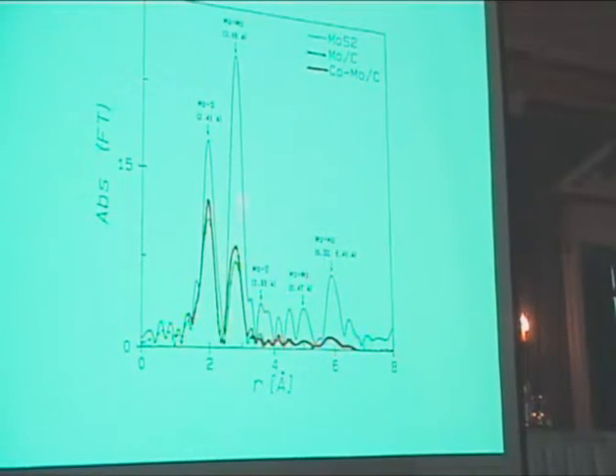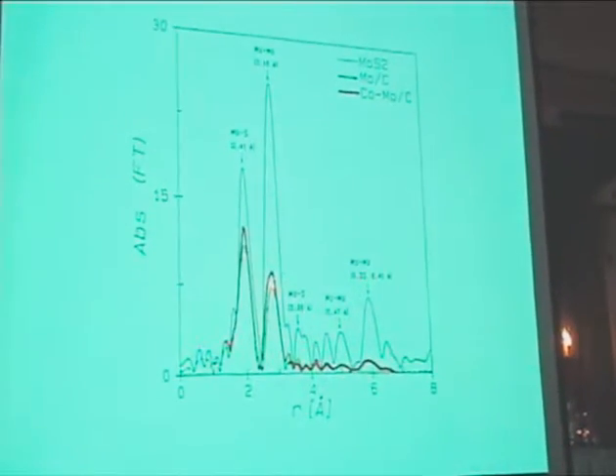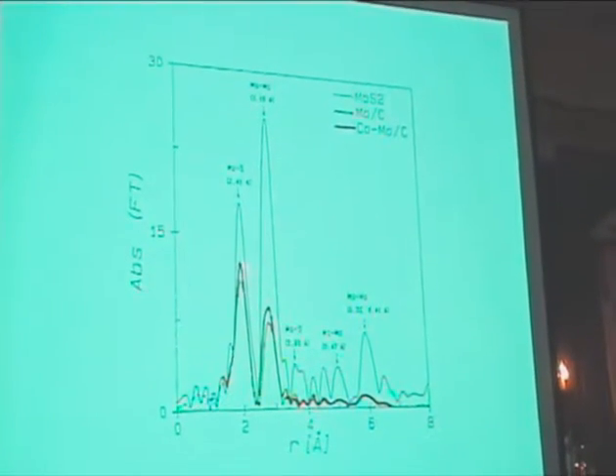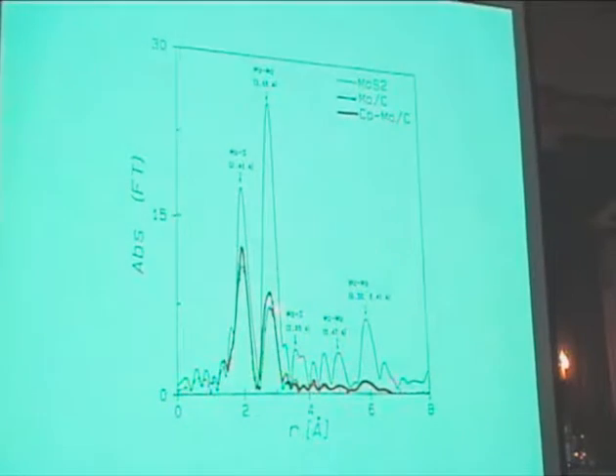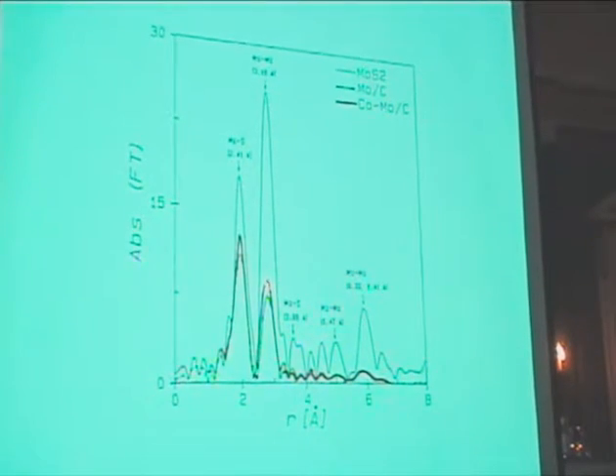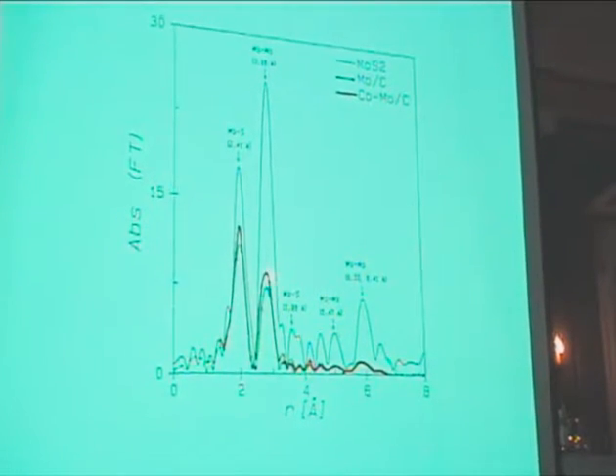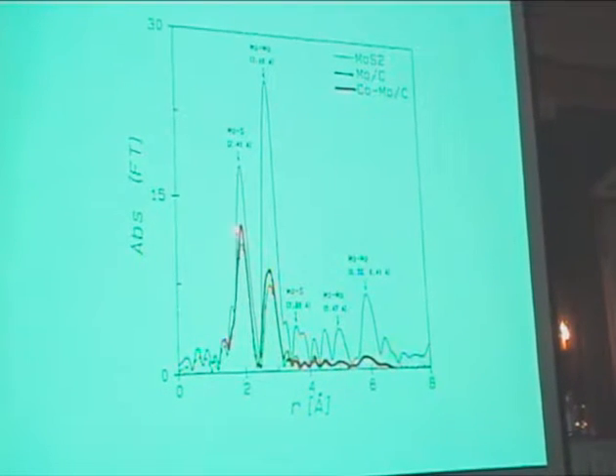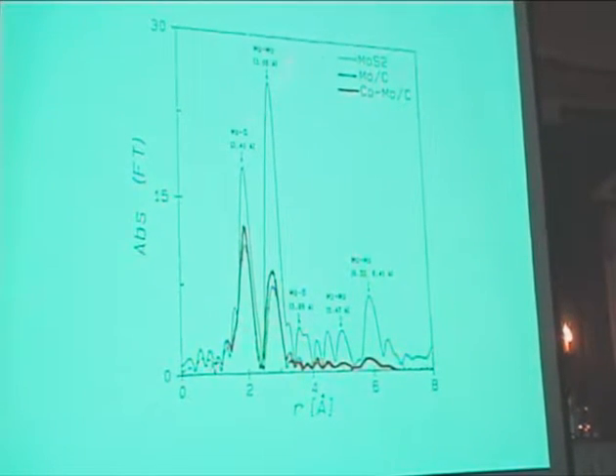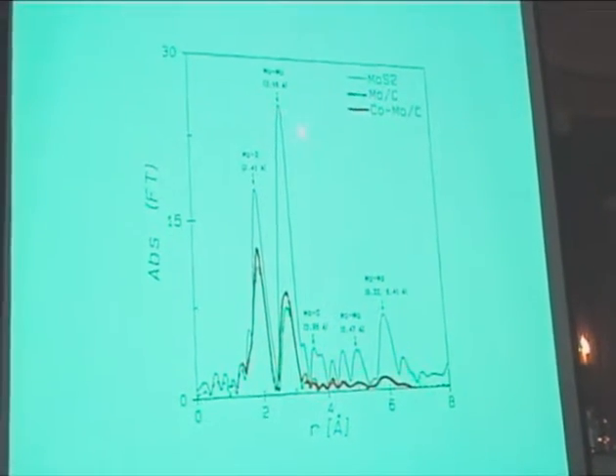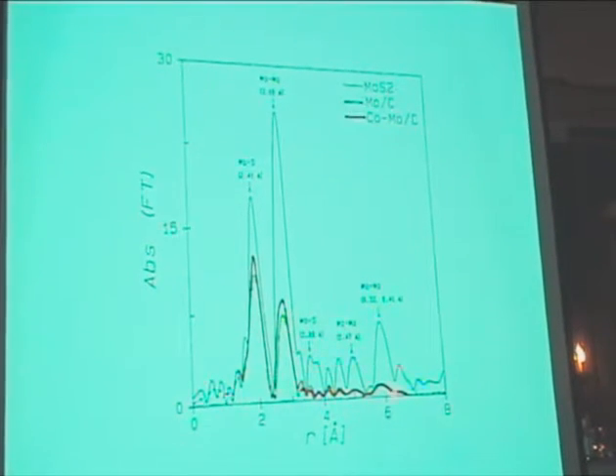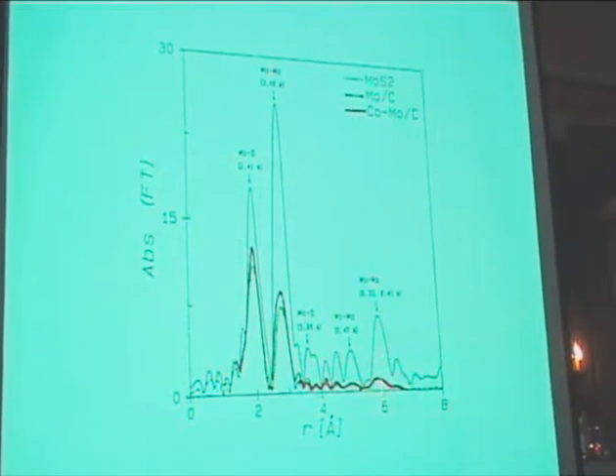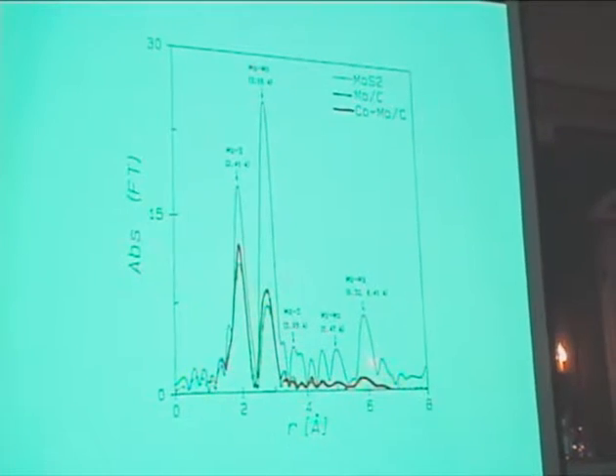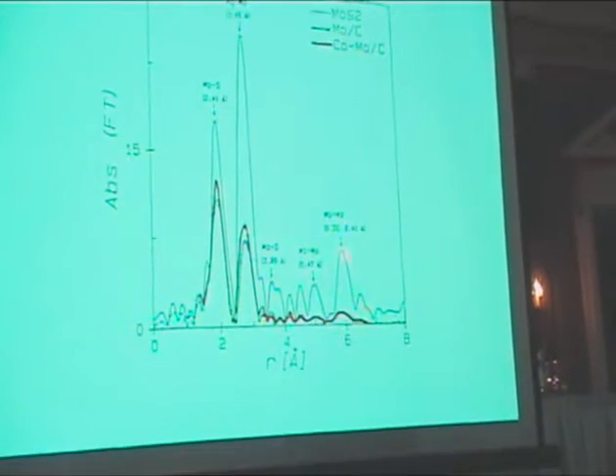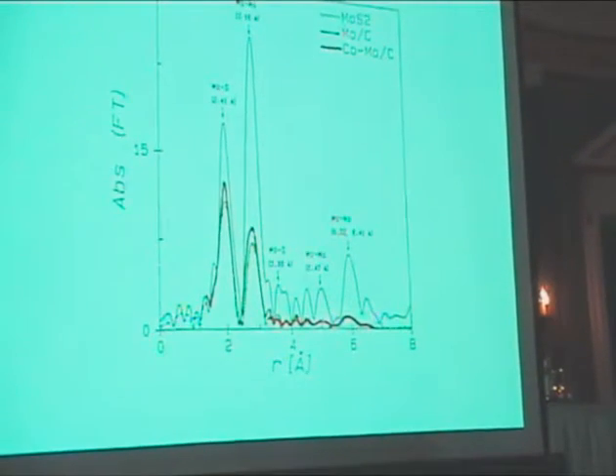The second peak does go down. And it's also now lower than the first peak. Look at that. And this is an important point in my analysis. Take notice that the second peak is now lower in intensity, peak intensity, than the first peak. Whereas in the single crystal, it's the reverse. All the other peaks are more or less gone, but for this double scattering peak. That is still there. It was quite intense in the single crystal, and you keep something.